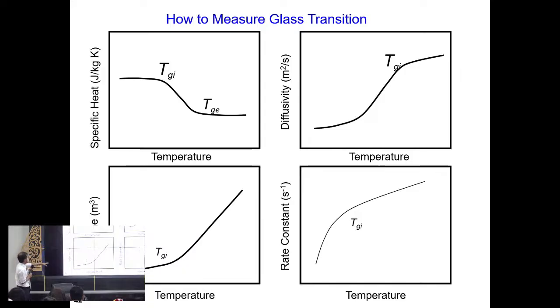Specific heat, volume, rate constant, diffusivity. When we want to get the glass transition temperature, it is not easy to get. But put the powder in a glass container and then measure the environment humidity. When you see the aggregated protein, the stage of very stable free-flowing powder and then aggregated, those boundary temperature is the glass transition temperature.